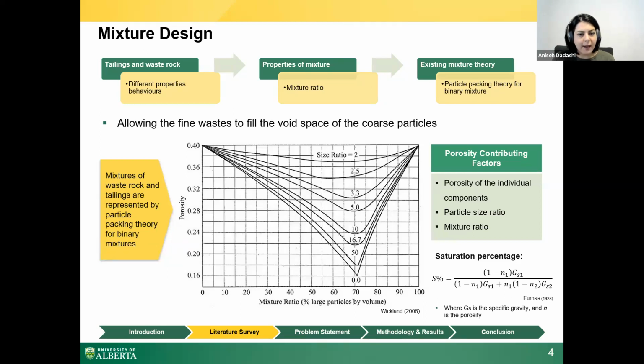As you can see in the graph, other than porosity of parent material, the mixture ratio and particle size ratio significantly affect the porosity of the mixture. In this figure, it is assumed that the porosity of parent material is 0.4. I use the equation in the bottom right from particle packing theory to find the saturation percentage of my mixture, which is based on the porosity and specific gravity of my parent material.